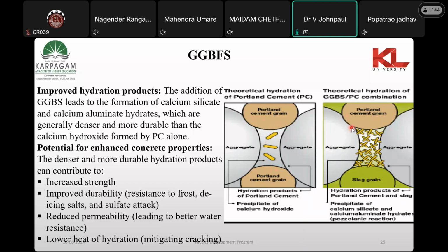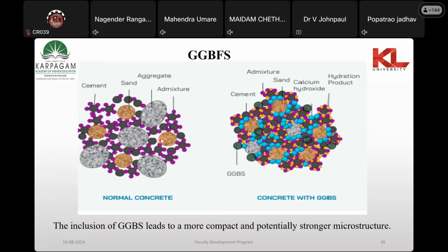Due to the improved hydration reactions, the formation happens in the concrete. If you just look at the normal concrete on the left side, there will be porosity. If the porosity is connected, there will be points where water can penetrate or air can penetrate. If it is RCC, there is a chance for durability problems because it starts to corrode due to the penetration of air and water. And if you look at the picture of concrete with GGBS, there are closely packed ITZ, interfacial transition zone, because of the hydration products which formed during the hydration process. So it's a strong